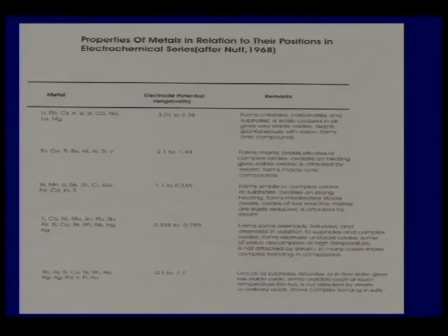Thus, the alkali or alkaline earth metals are mostly found as chlorides, carbonates or sulfates. Simple oxides of these metals are, however, rare, as they will react with other acidic oxides such as silica. So, they will end up forming minerals such as aluminous silicates and silicates.